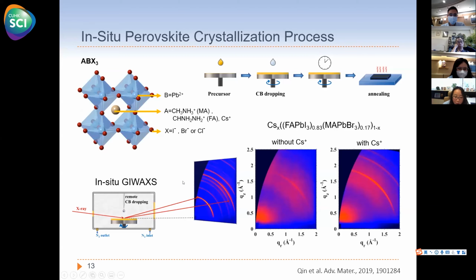Okay, so we are trying to mimic the fabrication conditions, like spin coating, dropping the anti-solvent, spin coating, and annealing, to observe the crystallization pathway of this perovskite solar cell.